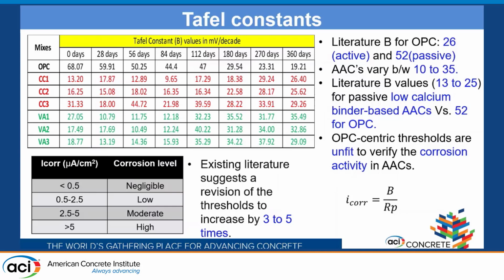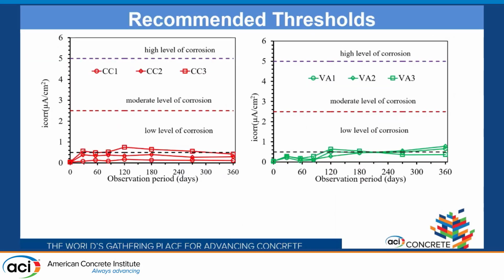The existing literature asks to make these thresholds more accommodative by 3 to 5 times. In my case, I have made them more flexible by 5 times. So now corrosion activity would be suggested above 5 μA per centimeter square, and there would be high chances of corrosion by that time. These are the recommended thresholds. We see that they work well in predicting the corrosion activity for our AAC systems. They are showing low to negligible levels of corrosion. However, with time we will gain more data for the active Tafel constant, and we will come up with more refined thresholds to predict the corrosion activity with quite good accuracy.